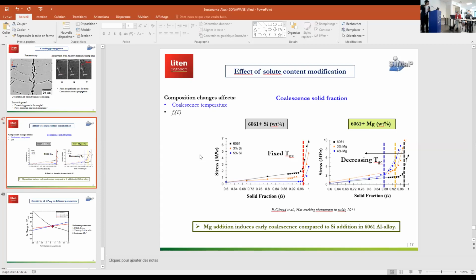For example, the dendrites are starting to get connected, and then you have liquid films which are forming continuously. And at the moment when coalescence takes place, these liquid films get disintegrated into different smaller pockets. Exactly, pockets. And it's a 3D effect. 3D effect, true. Yeah. So, in fact, the worst liquid films are those which are continuous, and yeah, it's a transition, definitely.